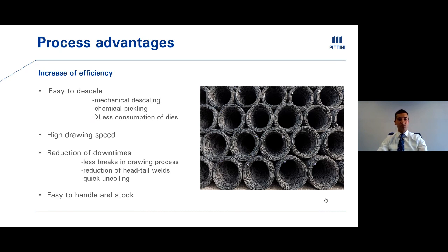Efficiency is a result of many factors. Among others, for instance, an easier descaling of the wire rod, both for mechanical descaling and chemical pickling. This is important in the process and is observed also in the lower consumption of dies. In terms of efficiency, a high drawing speed is also appreciated. A reduction of downtimes is observed thanks to fewer breaks in the drawing process, reduction of the weld's head and tail, and a fast uncoiling. Also, the handling and stocking of wire rod is optimized due to the 2.5 ton compact coil.